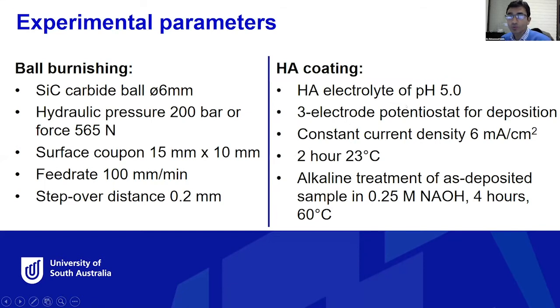In terms of the HA coating, at the beginning we had an electrolyte, a combination of the HA composition, with pH 5. We used the electrochemical deposition process here, at a constant current density of 6 milliamp per centimeter squared for 2 hours at 23 degrees centigrade, so pretty much room temperature.